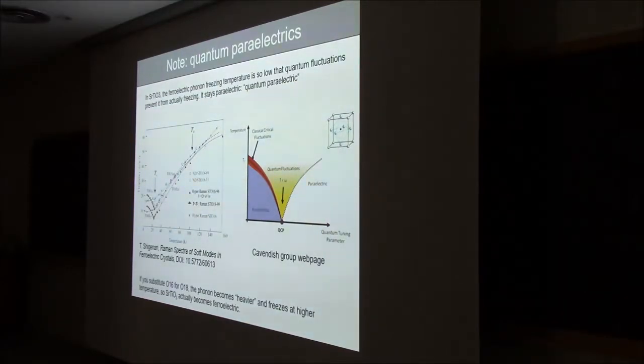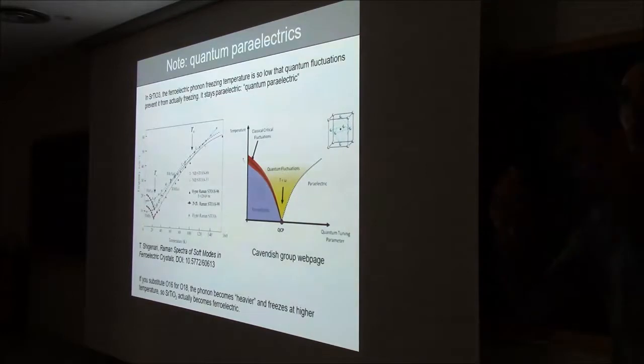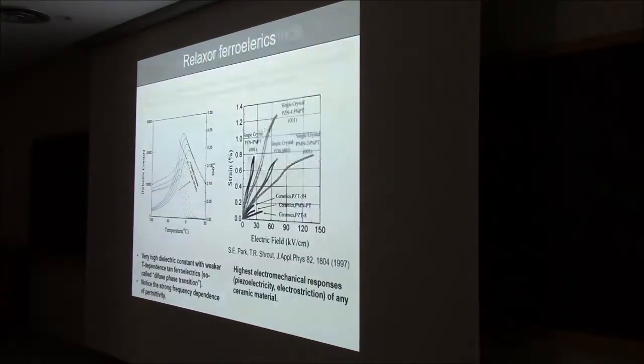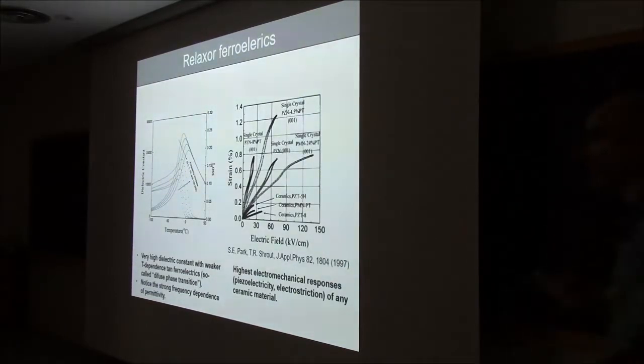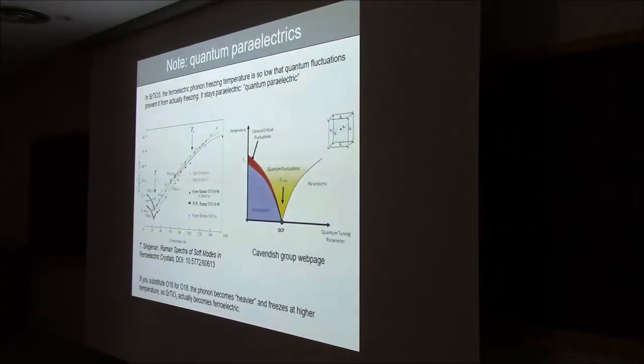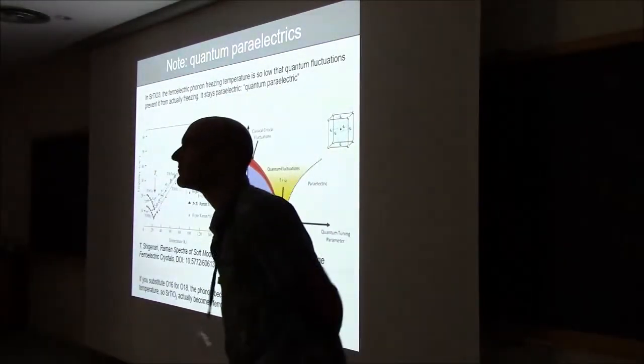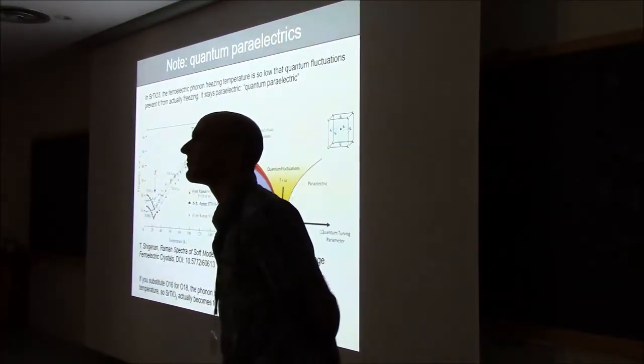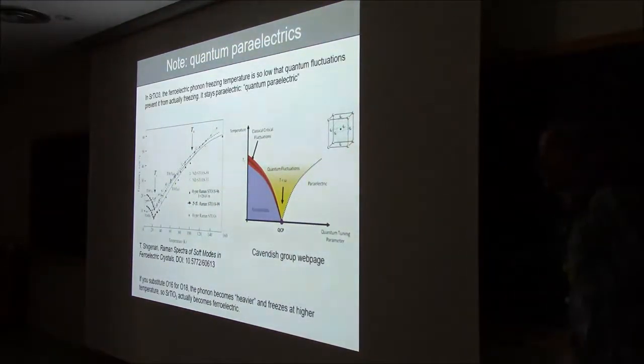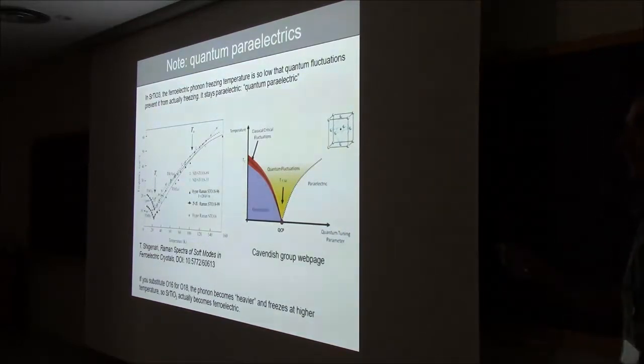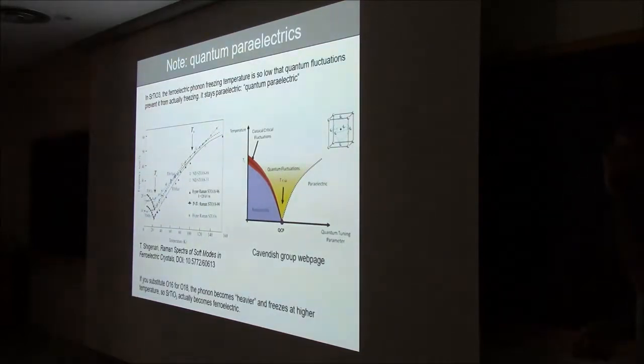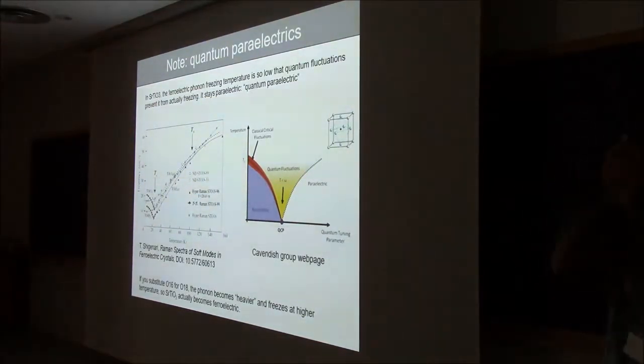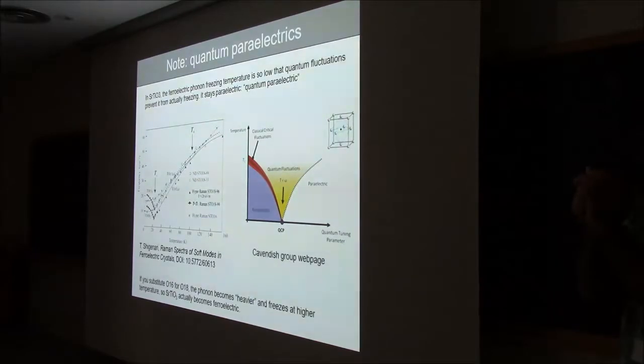Okay, so quantum paraelectrics is an almost ferroelectric kind of family of materials. Another almost ferroelectric, sorry. As you mentioned about the oxygen effect, how about the A-site strontium effect? Yeah, that has been done. If you want to do this experiment more cheaply, what you do is you substitute the strontium by a tiny amount of barium to make it bigger, or calcium to make it smaller. And either of them will work to turn your material into ferroelectric. It's just less cool, but it does the trick.